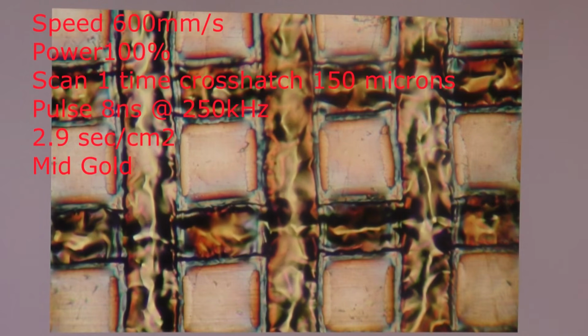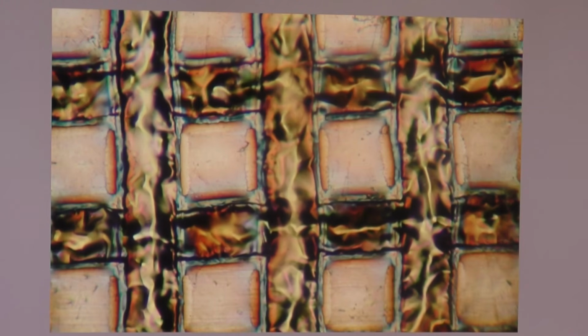It's quite a light, bright gold, but you've got colour in the beam as well there. That's an 8 nanosecond beam. So we're not doing as much damage with the beam itself, and that's why we can't see the striations in the bottom of the beam, because these are running at 250 kilohertz. And we're running the whole thing at 600 millimeters, which is quite slow, relatively speaking. But look, here we've got enough heat to produce blue round the edge of our square. So that's one of the very fast golds that I can produce. Takes about 2.9 or 3 seconds per square centimetre.